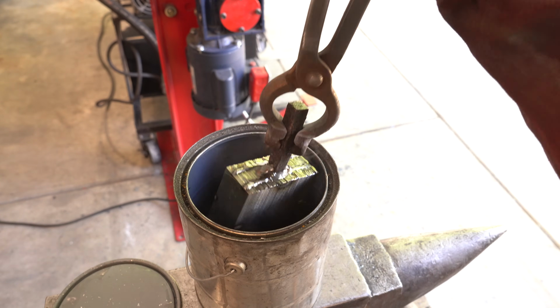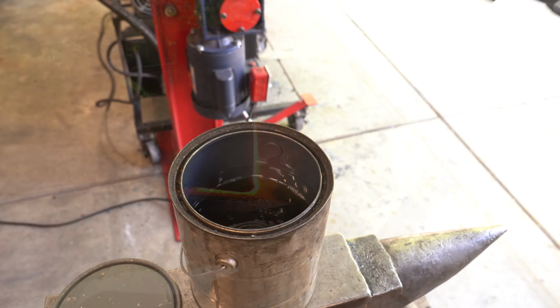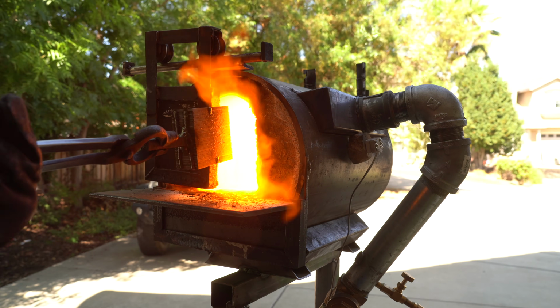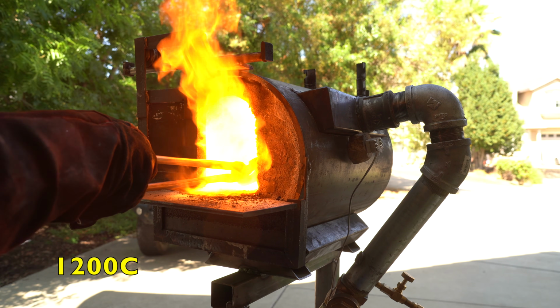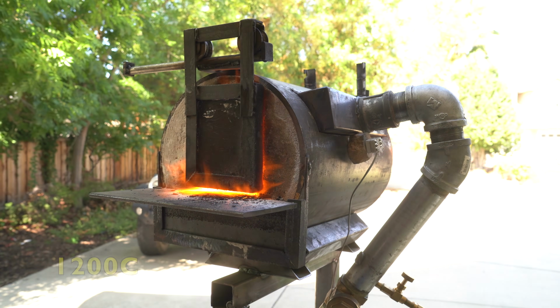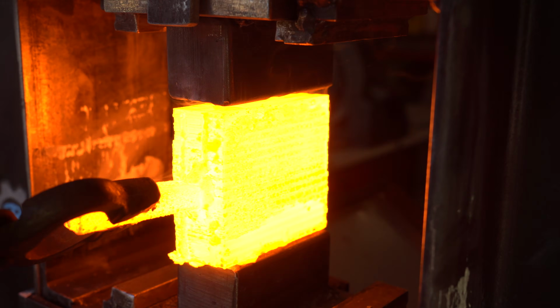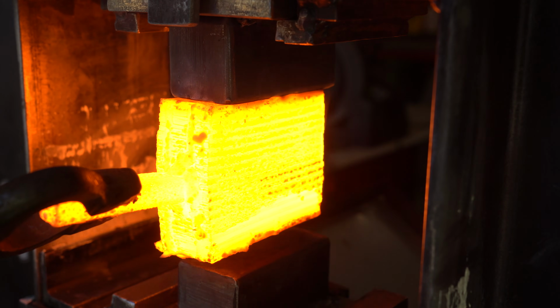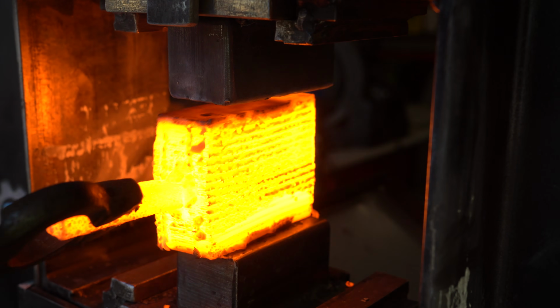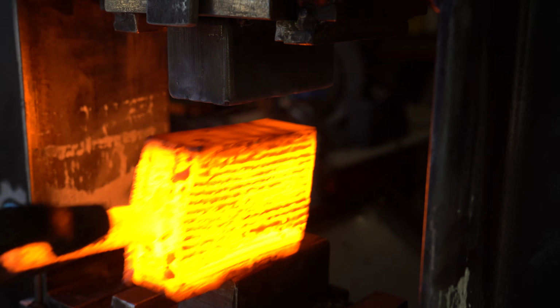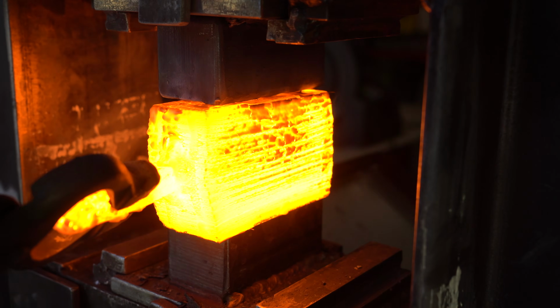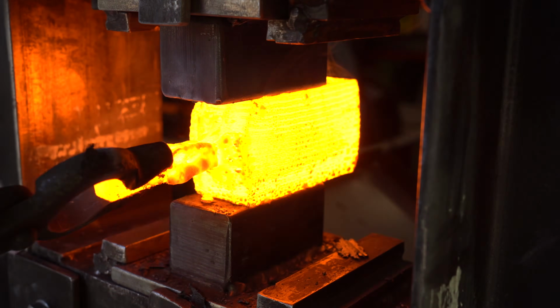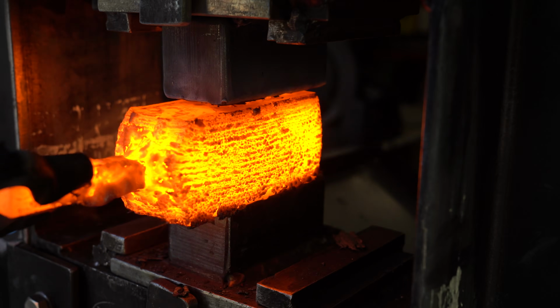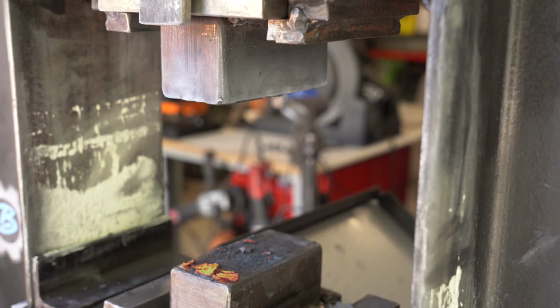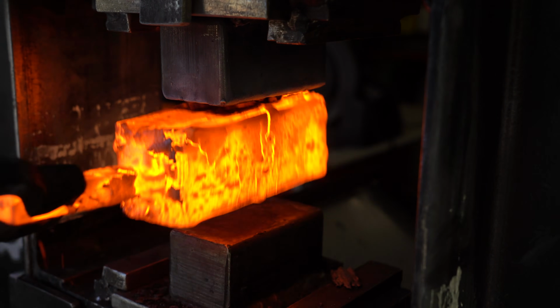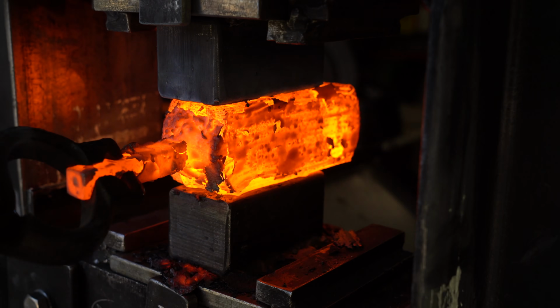After welding up this 35 layer billet, it goes into some kerosene to help with the forge weld and into a really hot forge, probably close to 2200 degrees Fahrenheit. We want to take it easy for the first couple of heats just to set the weld. Now that I've set the forge weld, we can be a little more aggressive, even pressing it on the sides.